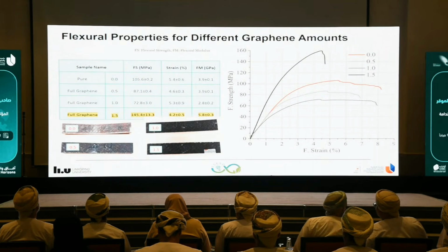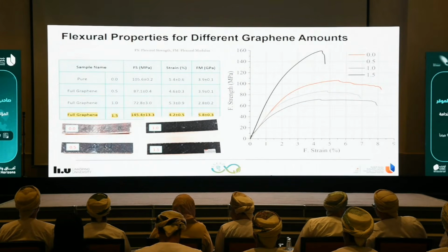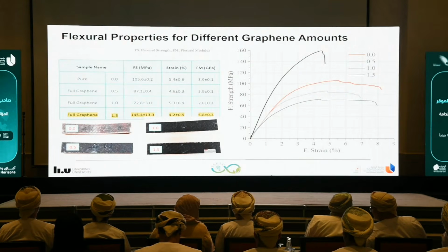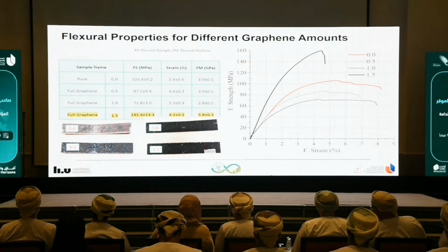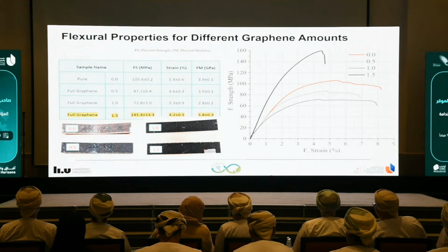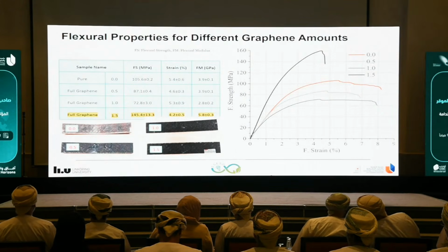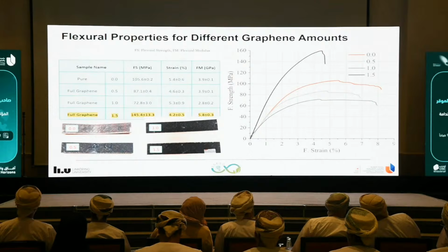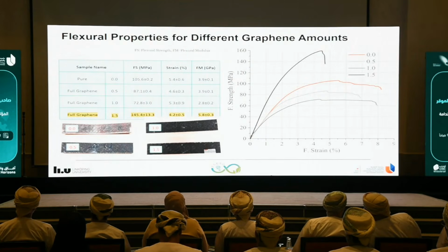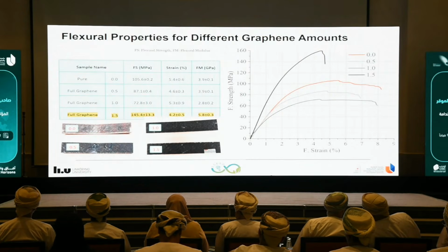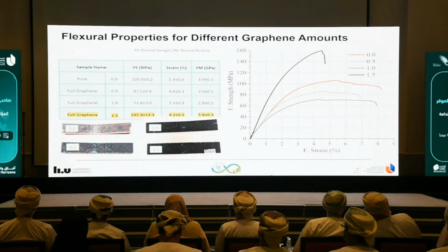We also saw similar results when we did water absorption. So the material which was coated at 1.5% absorbed less water. Then we decided from that point to use 1.5% as the optimum coating. We have also coated the material with higher than 1.5%, but it didn't show good results. So there is an optimum value, and if you increase the concentration a little bit more than the optimum value, then the properties will go down again. So for that reason, we decided to keep 1.5%.